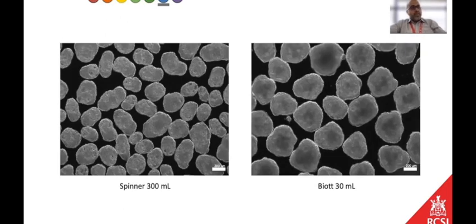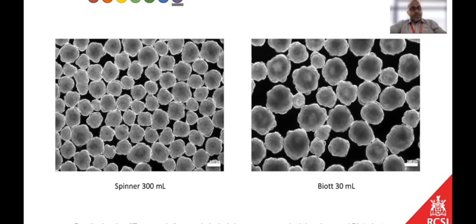Now we end up with the endocrine progenitors. These are more lumpy and look like an irregular shape, and often they resemble a peanut shape, and they're a little bit larger in size. And then we reach our stem cell derived beta cells. As you can see, this is stage 6, day 10, so it's a little bit older. They appear more fluffy, like cotton balls, but this is how it should look. And so this is the end stage. You can see that there is a size difference, but the morphology and the general structure is the same.